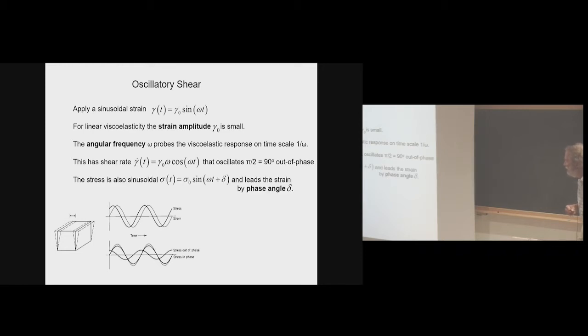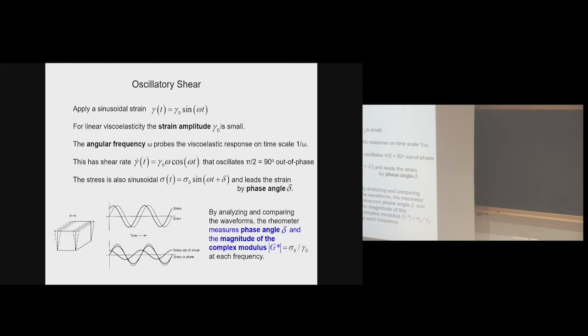That's important. And the stress is generally going to be sinusoidal with the same frequency, but have a phase lag, delta. The stress actually, you can see in the bottom, in the heavy line, is leading the strain by phase angle delta. We can think about two simple limits of that.